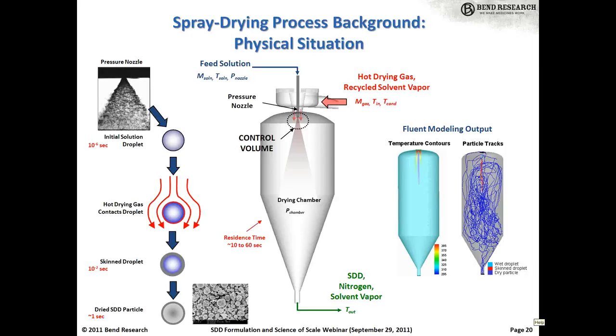Most of the polymers that we work with for spray dried dispersions are film forming polymers that form a skin almost immediately as the solvent begins to evaporate. And that skin acts as a barrier or resistance to diffusion of the solvent from the interior of the droplet to the exterior. And then as the drying process proceeds, that skin thickens and hardens until you end up with your final spray dried particle. Of course, the rate or temperatures at which that drying process happens can greatly impact the morphology of the resulting SDD, and we'll talk about that in a few slides here.